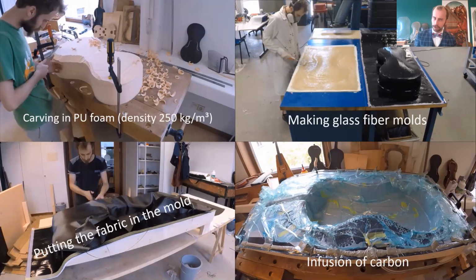So first I carved my entire instruments from a PU foam, density about 250 kilograms per cubic meter. And as you can see here, you have the little shavings that you also have with wood. So it works in a very similar way to wood. You have no grain structure, of course, but you can shape the cello or the violin in a very conventional way. Then on those patterns, I put the glass fiber molds. So glass fiber and polyester together, they harden up, they become a composite, and they become very stiff. And then that mold I can use to make my composite materials directly into a product.